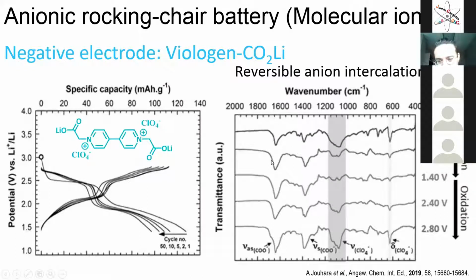So you can see here that you have the carboxylate remain unchanged during the redox process. So the carboxylates here are not participating in the redox reaction, but instead you can see the band around 600, which belongs to the perchlorate anions, appearing and disappearing. And this actually proves that you are taking in and out perchlorate anions, and this proves the anionic redox mechanism.